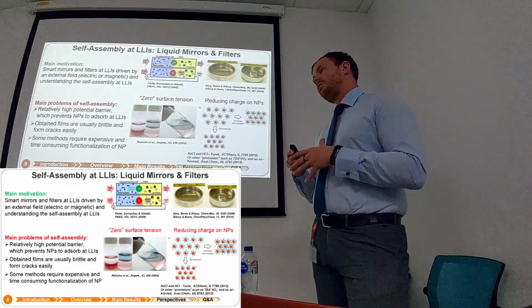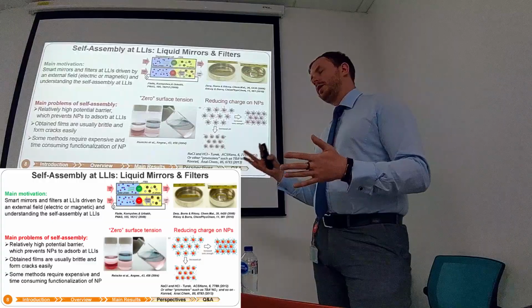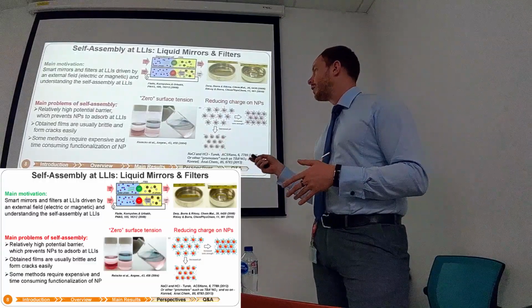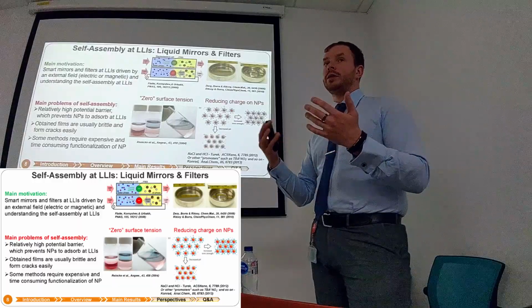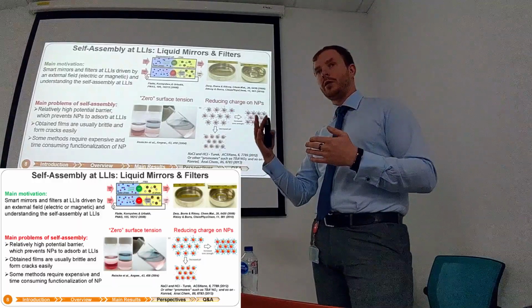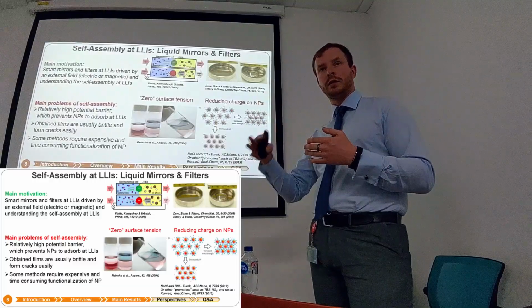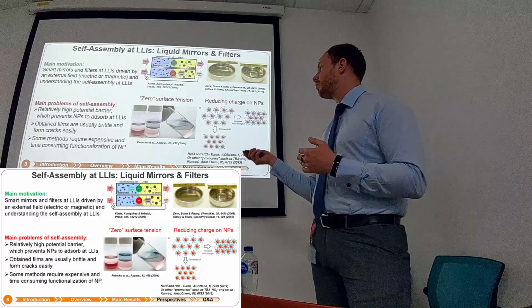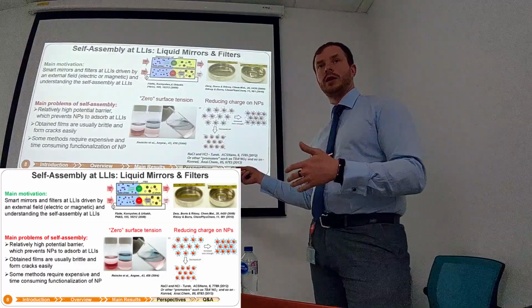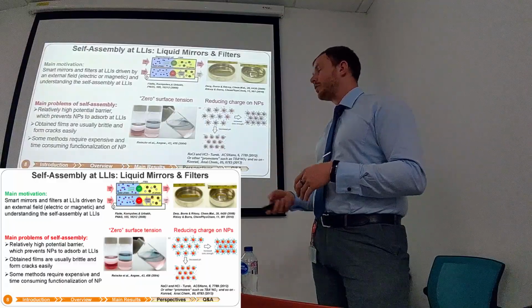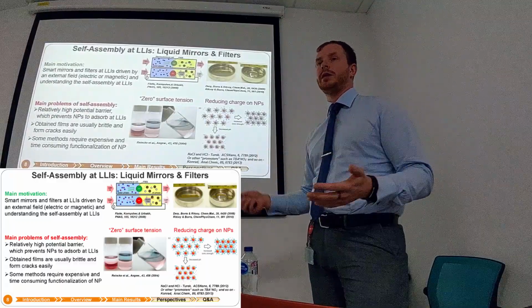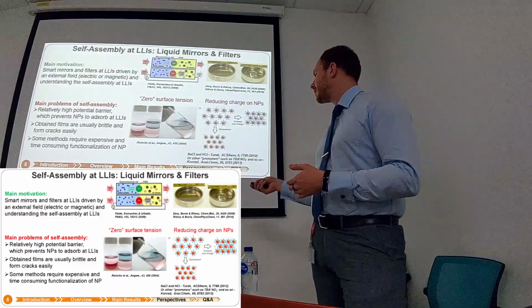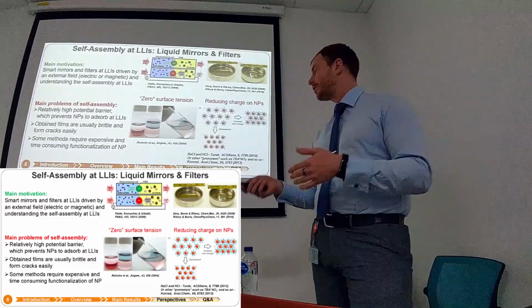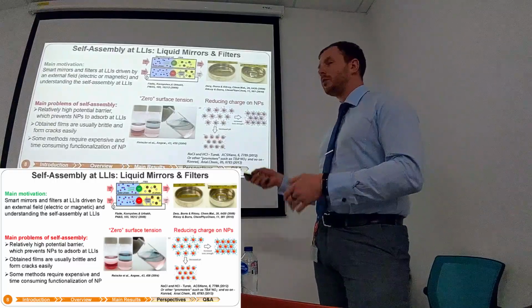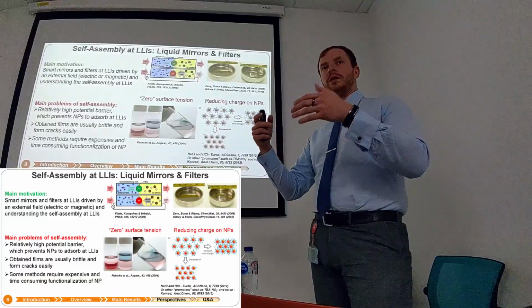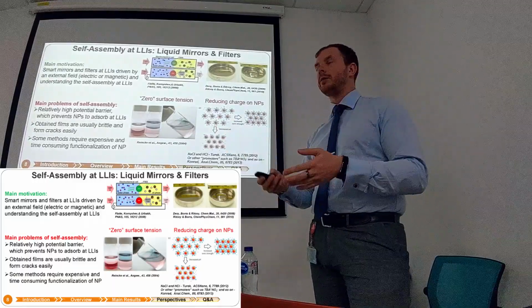I classify all the self-assembly methods in two big groups. The first one is zero surface tension, when you somehow form a third phase, where the properties of the liquids change gradually, not stepwise as at a liquid-liquid interface. For example, you add some ethanol, you mix, and you assemble nanoparticles. Another one is reducing the charge of nanoparticles. This can be done by different means, let's say promoters, salts, additions, and so on, but the idea is similar. You increase the concentration of the salt, you decrease the repulsive forces between nanoparticles, and you assemble them.